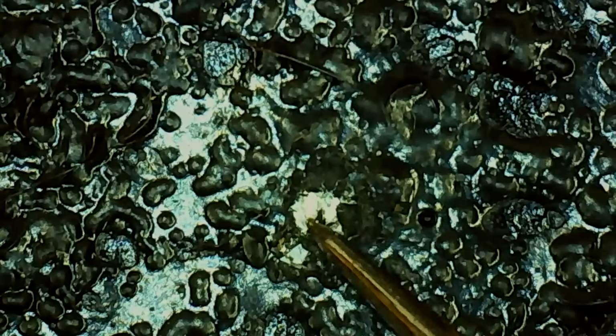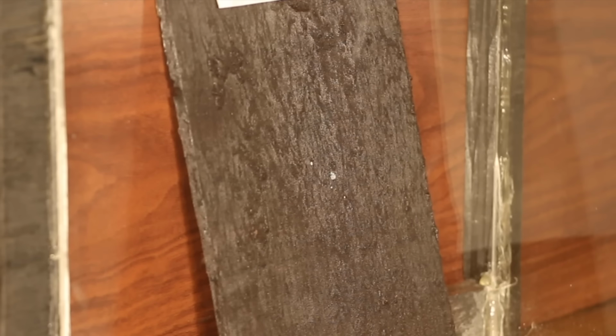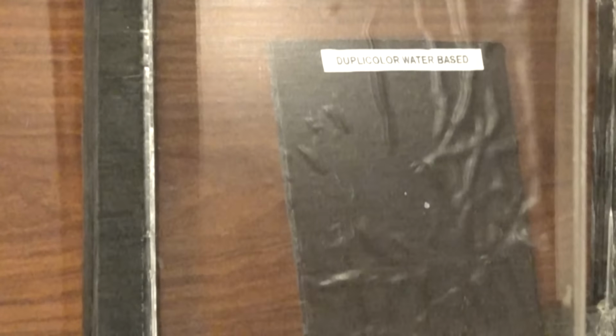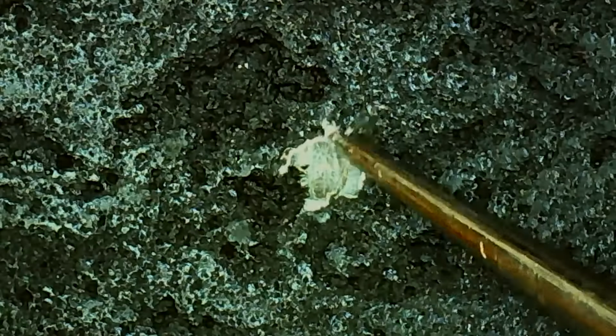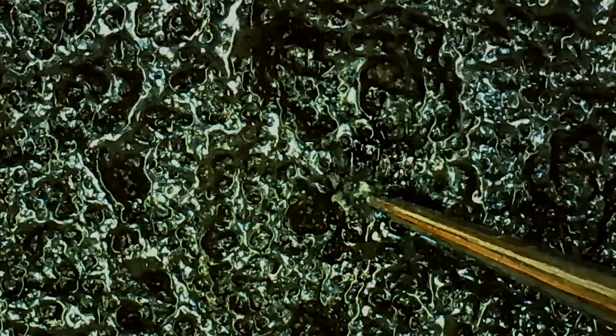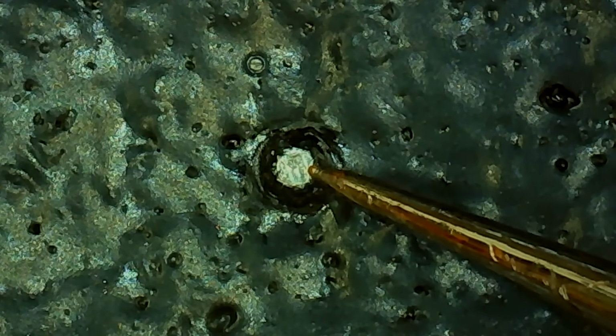Raptor did quite a bit better at ambient temperature as well, with 3.2 millimeters of damage. The water-based Dupli-Color also improved slightly at 3.21 millimeters. The warmer temperature seems to have allowed Herculiner to soften just enough for the steel ball to penetrate the bed liner material. The warmer temperature helped POR-15 quite a bit with only 1.5 millimeters of damage.